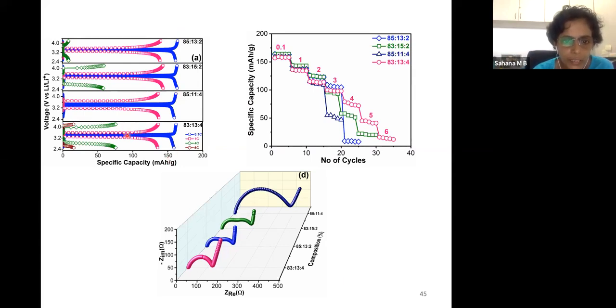Now you can see here that charging and discharging take place at a similar voltage. That is, both of them take place at 3 point something, like 3.5 or 3.4, and the difference in the average charging voltage and discharging voltage is minimum. Now let's go to the red color one. Here we increase the charging rate from 0.1C to 1C. You can see here the charging happens at a slightly higher voltage and the discharging happens at a slightly lower voltage. So the meaning of this is you're charging at high voltage and discharging at lower voltage. So the efficiency of the cell goes down. You're losing some portion of the energy.